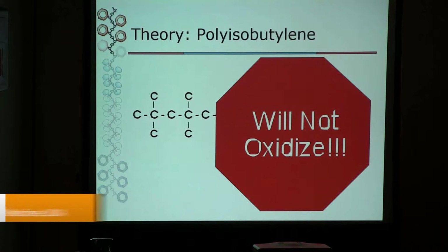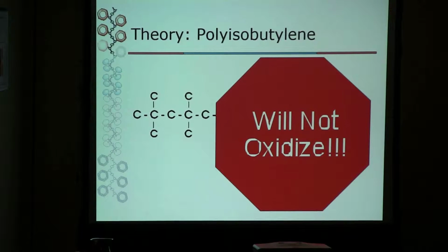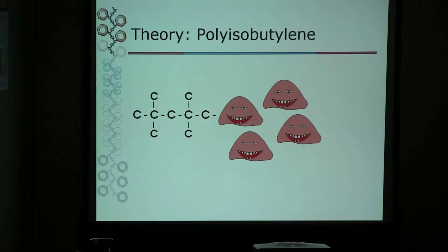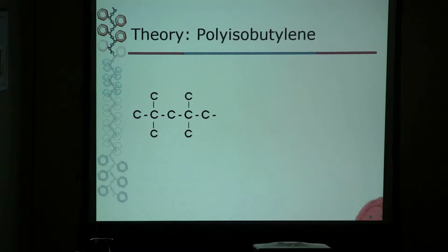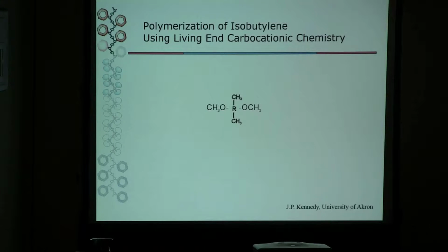So you will not oxidize polyisobutylene. That's called polyisobutylene. And if you don't oxidize, your macrophages don't come around. They certainly don't stick around. So we make this in our laboratory, and we synthesize a seed molecule, and at minus 80 centigrade, we put a plus charge on each end, and this is called living end carbocationic chemistry, and the mechanism of reaction was licensed from Joe Kennedy's lab at the University of Akron.